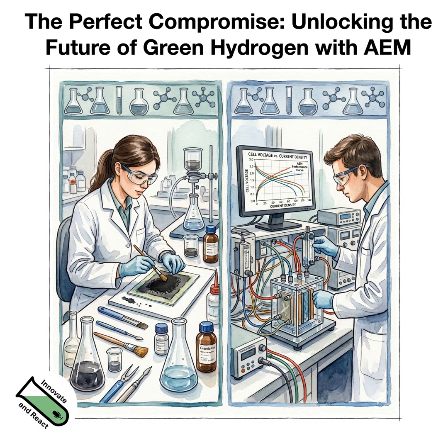If one does catalyst research on a rotating disc electrode, then you do your LSVs and your CVs to get something for the intrinsic activity. You can calculate your Tafel slopes, which tells you a little bit of how active. I try to not use the word active. How much your catalyst really wants to do what it needs to. Current density. Yeah, because I don't like the word activity, because activity gets oftentimes jumbled together with other words. I think it's not accurate enough.